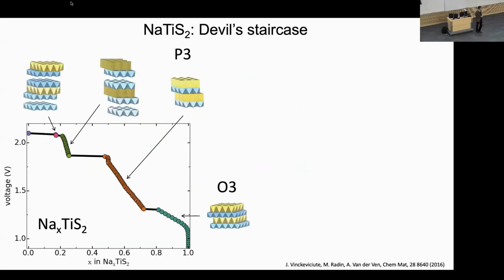But it gets very interesting when you look at sodium. If you put sodium between the same layered materials, sodium is bigger, and because it's bigger, it causes much more dramatic changes in the host compound as you change the sodium composition. This notation here just reflects different stacking sequences of the TiS2 sheets. These are TiS2 sheets, and the yellow are the sodium ions. In this O3 stacking, you have a particular stacking of these sheets such that the sites that sodium can fill are octahedrally coordinated. And that's why this is O.